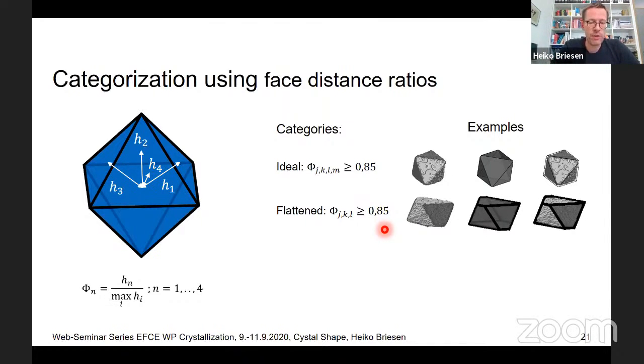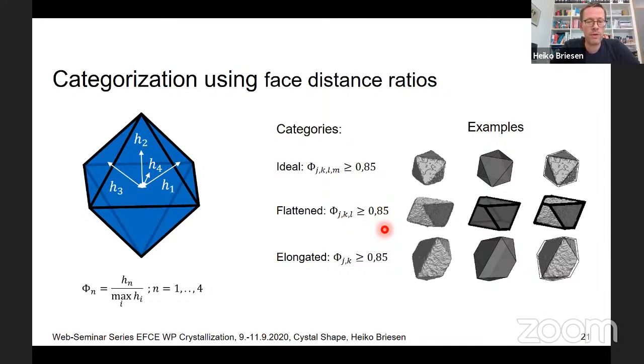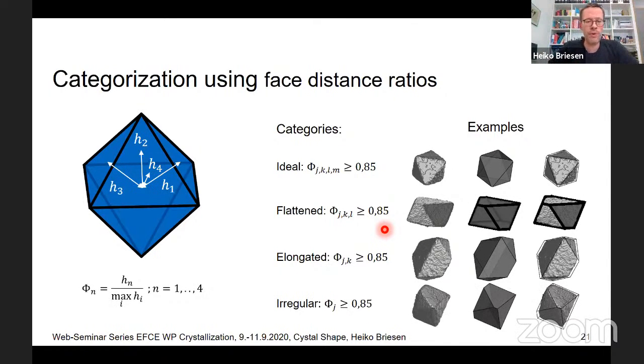You can imagine how the story goes. We also did this to see how it looks when you have 2. So you squeeze 2 sides, you end up with an elongated shape. And if you have only one of them larger than 0.85, which is basically the one which is per definition there, then you end up with pretty irregular shapes.